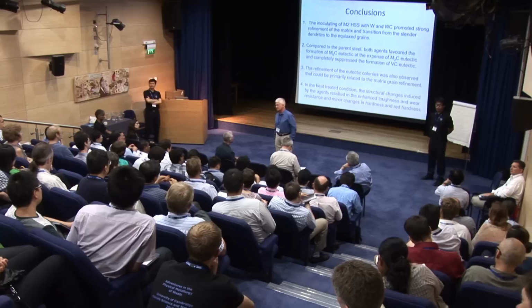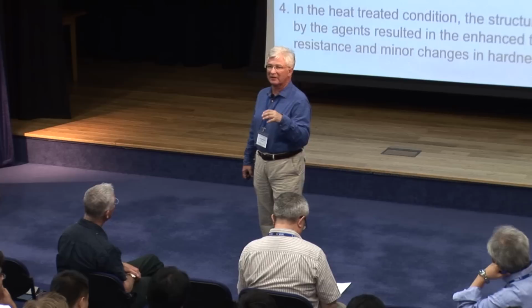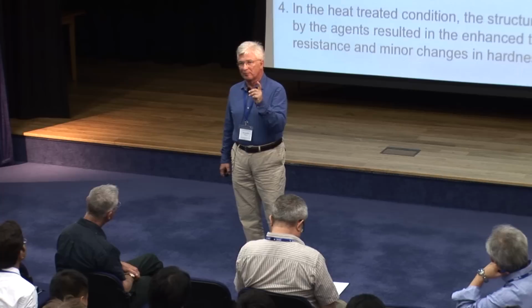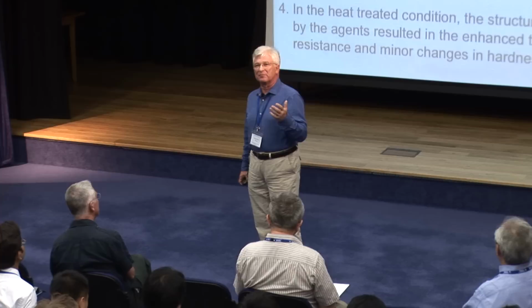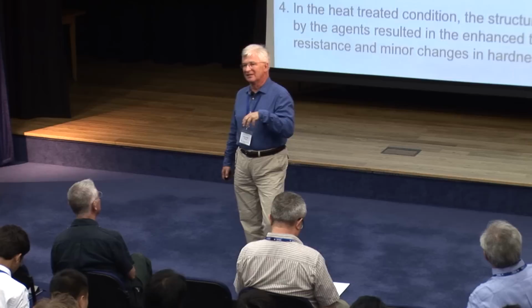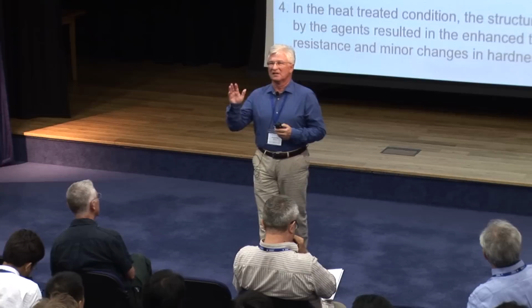Yes, of course. It's a very important thing, because the size of carbides, even in the as-cast state or, for example, in wrought material after hot plastic deformation, is very important. For example, it's possible to improve carbide heterogeneity by using powder metallurgy. But in this case, the price is very, very high. And compared to the common wrought high-speed steels, the application of powder metallurgy high-speed steel is very, very low.